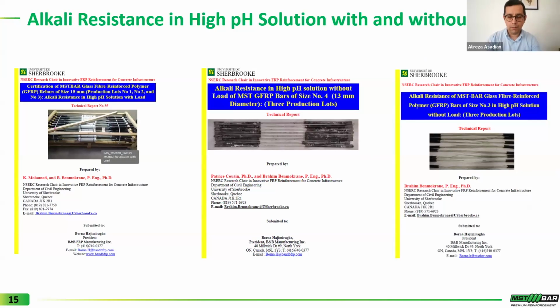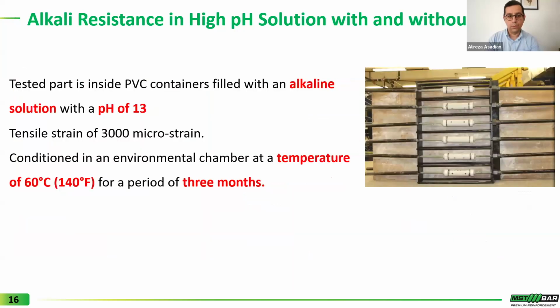So one of the durability tests that is done based on CSA S807 is resistance to alkali, and this test is done two ways: one with load and one without load. In the with-load test, the rebar is exposed to an alkali solution with a pH of around 13, very high pH values, and then it's under a constant stress of 3,000 microstrain, and the rebar is then conditioned in an environmental chamber at a temperature of 60 degrees Celsius, or 140 degrees Fahrenheit, for a period of 3 months, and